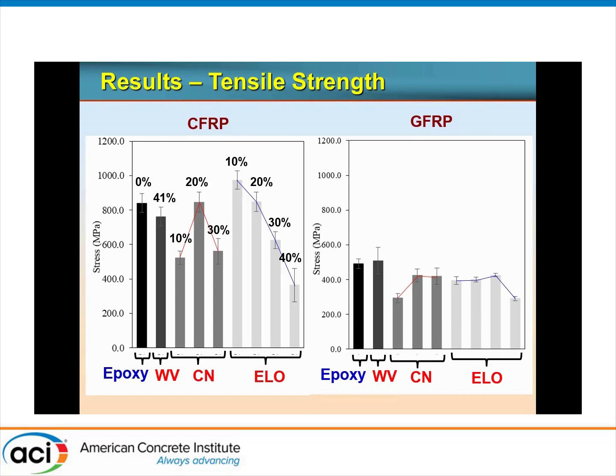possible tensile strengths. For the epoxidized linseed oil, it was actually interesting. The 10% had higher strengths than the epoxy, but then it drops gradually as you go to 40% bio. For the glass, somewhat similar but not quite the same trend. The last two types did not come all the way up to the level of the epoxy control. So that is the tensile strengths.